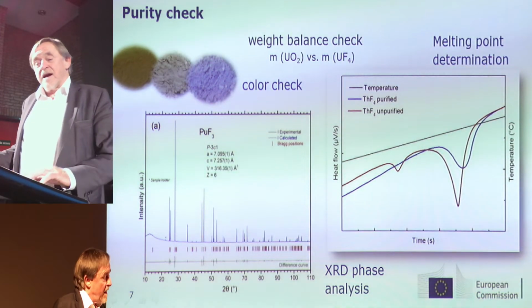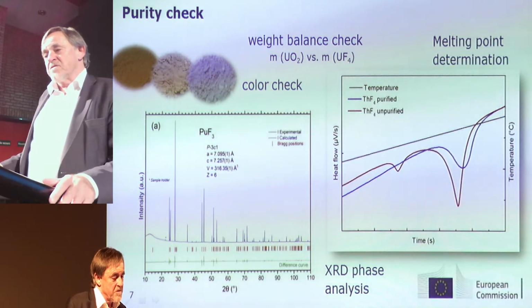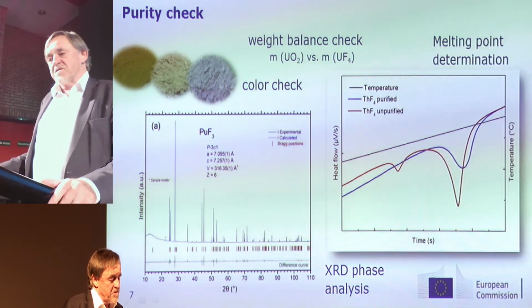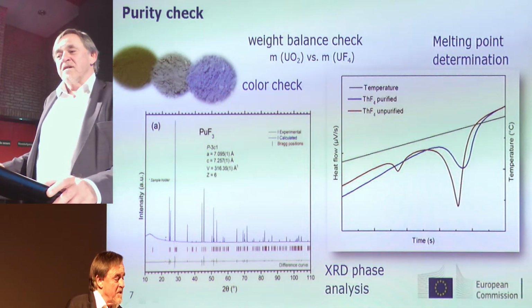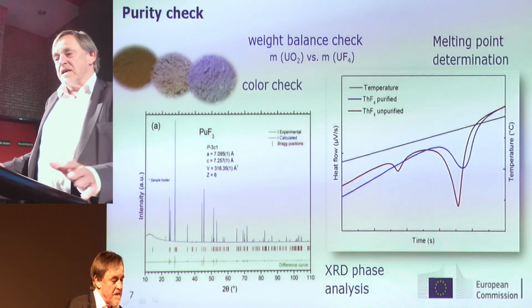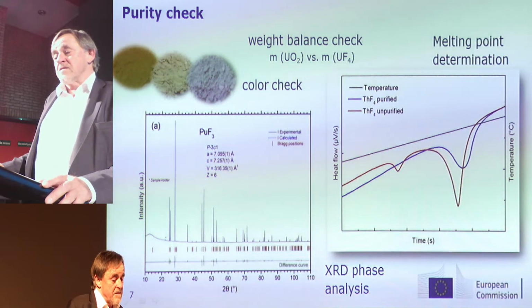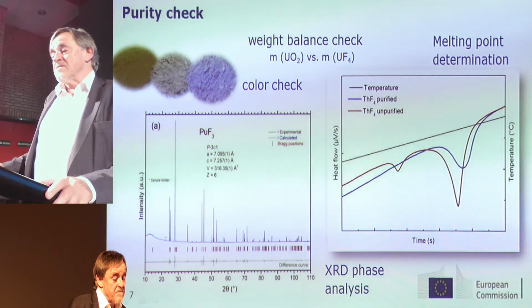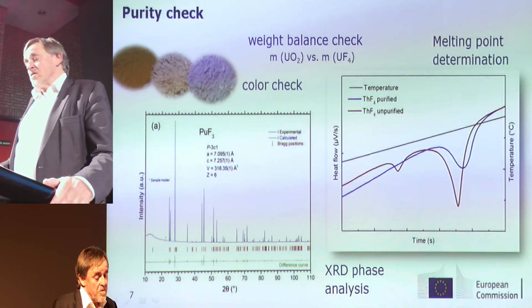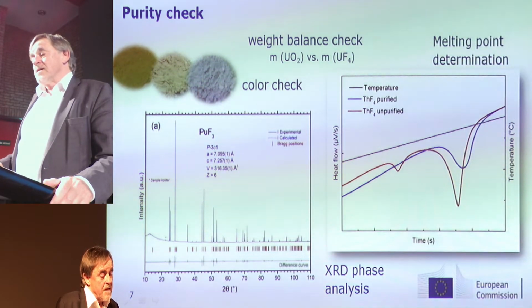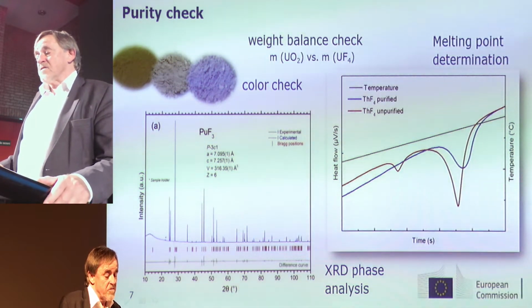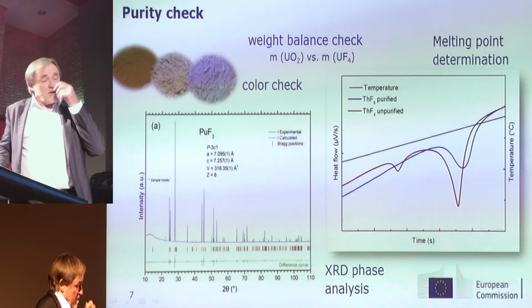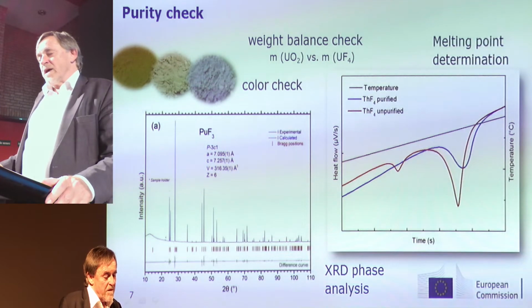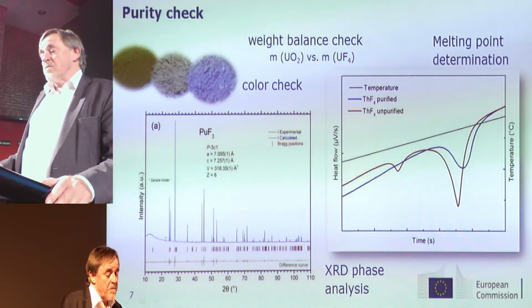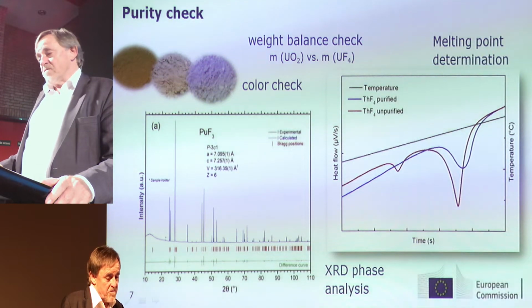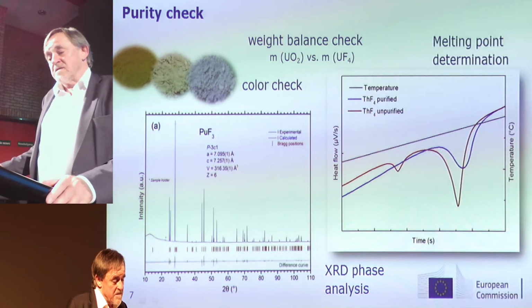So the first check after the synthesis of the starting materials, which is very important to be sure about the purity of this material that you have produced. The first one is the color check. You see from the color how complete your reaction is as a first indicator. Weight balance is a second indicator. And then we make this determination of the thermal gravimetry with this melting point determination. And we see that, for instance, in the case of the red curve, we have an incomplete reaction, so that we have still oxides present in this compound, and only in the blue curve we see that the fluorination, in this case of thorium fluoride, is complete.